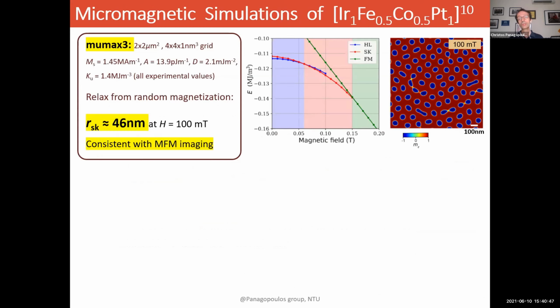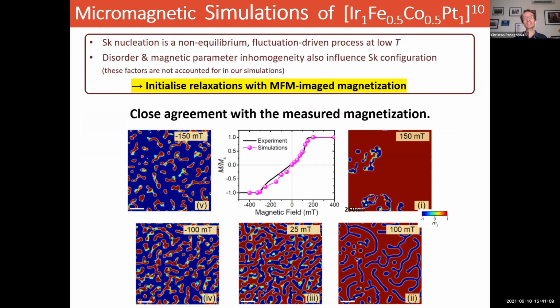So for the micromagnetic simulations of our heterostructure, we perform mumax, and we find that indeed we can calculate a radius of a skyrmion to be 46 nanometers. This is almost the same as the 47 nanometers that we measured from magnetic imaging in our samples. And we can initialize relaxation with the MFM imaged magnetization, and through these micromagnetic simulations, we can also calculate the bulk magnetization. And in the center, you can see the simulations in pink agreeing very well with the experiment shown in the black curve. So it looks like our simulations can reproduce our magnetic heterostructure and the magnetic texture configuration as a function of magnetic field very well.